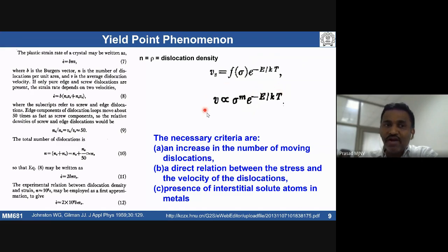So according to this model, they used the simple Orowan equation, which basically describes - I think in one of my previous lectures I said strain is proportional to rho, b, l. Here actually strain rate is basically b, and n is considered as rho, because I'm simply taking information from this paper, you can consider n equal to rho here. Rho is the dislocation density, b is the Burgers vector, v is the average dislocation velocity.